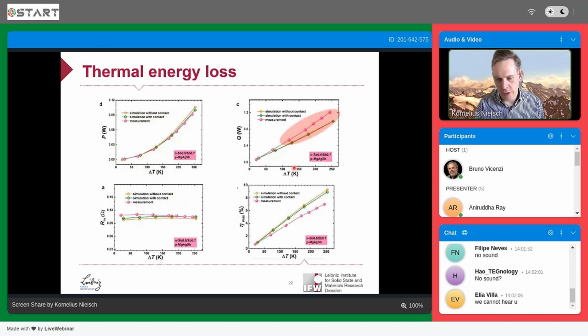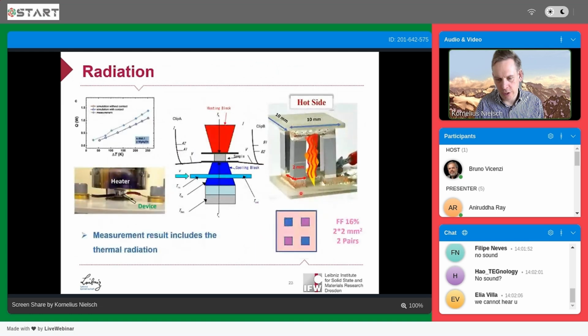We looked later on a bit more at the simulation, and what we obtained by simulation on what the losses are up to now and how we can further improve it. It turned out something can be done with improving the contact, but in general, the results are already rather promising in terms of the overall device. So we used another strategy and optimized the geometry of our overall device to obtain higher efficiencies and also higher power densities.